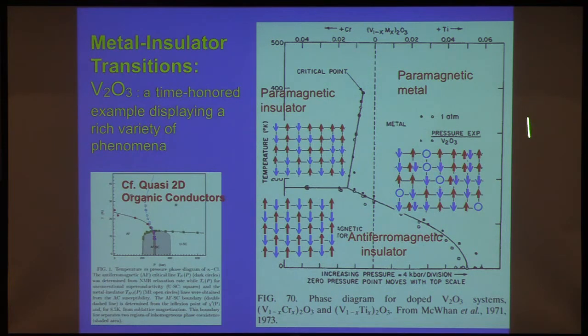This kind of physics with three phases, a paramagnetic insulator, a paramagnetic metal, and an antiferromagnetic insulator, is also found pretty much in the same manner in some of the organic conductors I alluded to in the introduction, where you have here a first order transition between two similar phases, and here it's even prettier because this metal actually wants to become a superconductor below a transition temperature which is only about 14 Kelvin, but which by the standards of the typical energy scales in this system is a pretty high Tc.